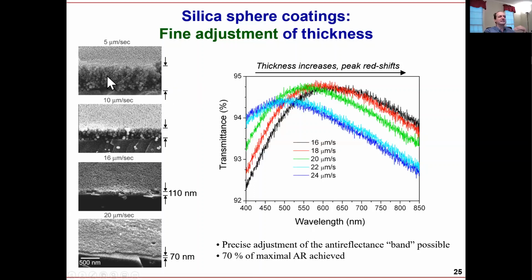You make those silica particles into a coating of a certain thickness. You are going to control the thickness, but your refractive index is not going to be controlled, because the refractive index is always going to be the refractive index of closely packed silica particles. So you are halfway there. You can control the thickness of that coating. What can you do next to control the refractive index? How do you control the refractive index of such a coating? What would be ideas in that regard?